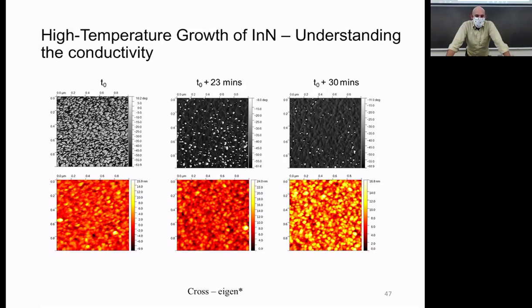But what happened was that the tip was interacting differently with the high parts of the sample than with the low parts of the sample. And that actually changed as we grounded the sample, which means that that was an electrical effect. The tip was being polarized by the sample because the sample had stored up charge on it. And that's not supposed to be the case. These samples are not supposed to store charge on them. So this was very confusing, and this is where I am right now. I want to understand what was going on with this.